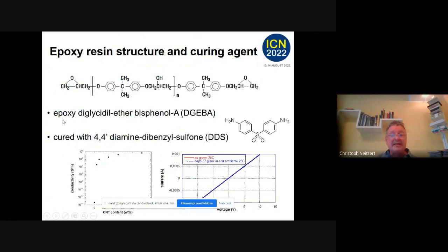So now we go to the next system, and it's epoxy. It's a normal epoxy ether with bisphenol A, and it's cured, and we get nanocomposites. Now we get a very highly conducting material. If you see here, this is the conductivity as a function of the nanotube content.